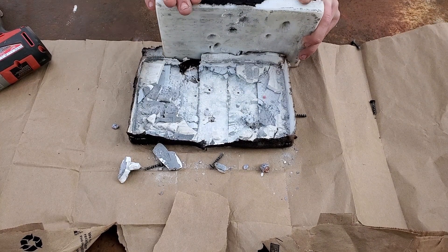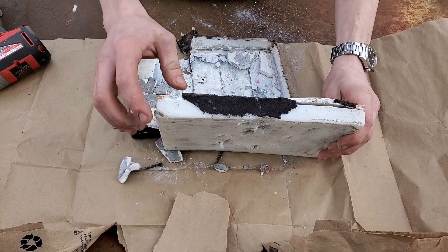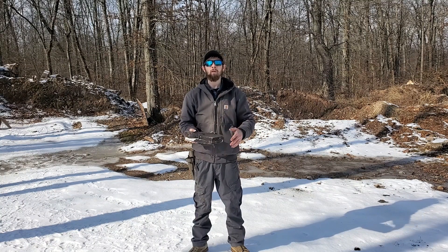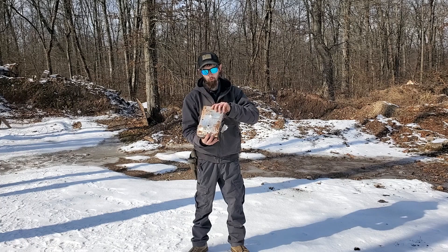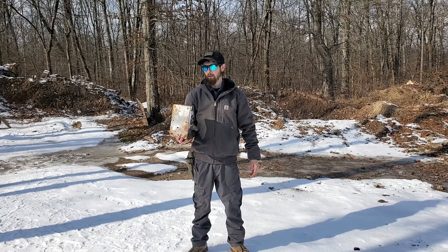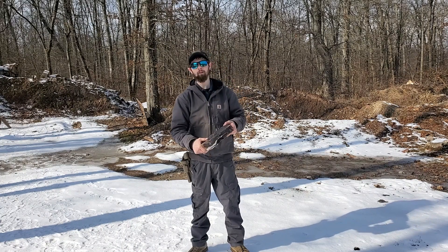This high-density polyethylene and aluminum plate is 9mm handgun rated. You go and put this ceramic in front of it and you've got a rifle-rated plate. Just these two plates together make it a Level 3. You go and slap that ceramic in front of it and it's Level 4. I haven't really tried it with any armor-penetrating rounds. But guys, this armor performed better than I ever could have hoped. We did have one pass-through, but that would have been passed over by NIJ standards because it was within an inch of another shot with no material there to stop anything. After that, it repetitively stopped every other round — .243, 9mm, 30-06. I shot the 30-06 first because I knew that was going to obliterate this plate, then a .243, a couple of 5.56, a couple of 9mm. This thing fared extremely well. It bent to hell, but for armor to perform as well as this, you can't ask for much more than that.